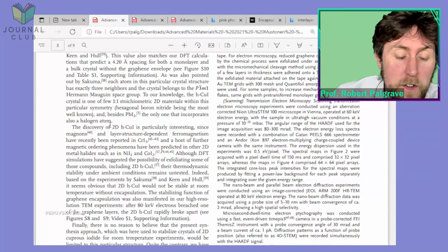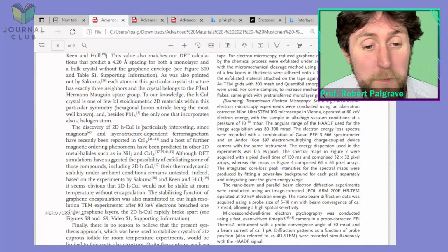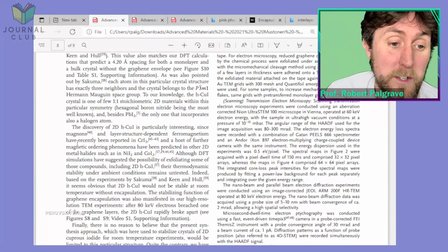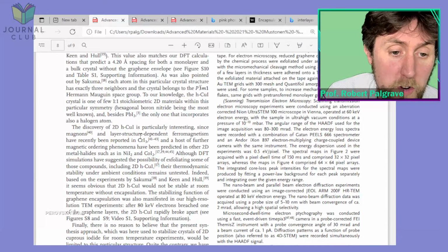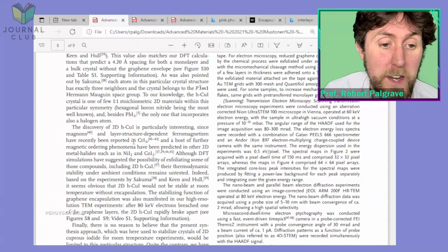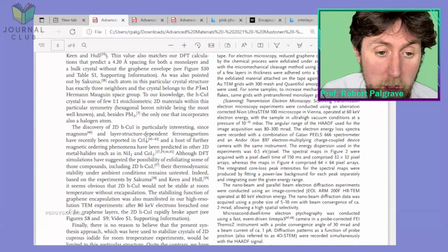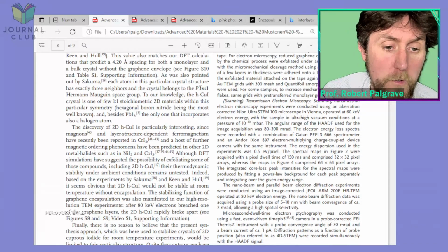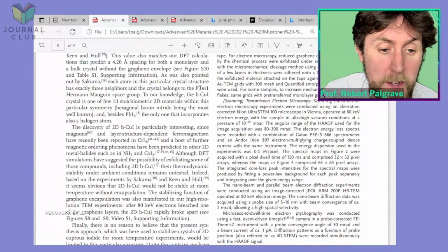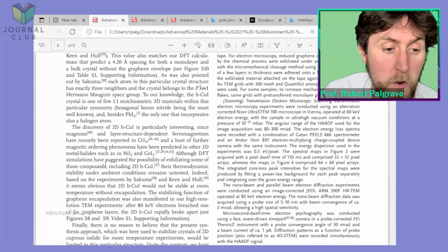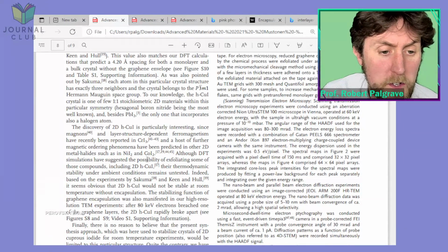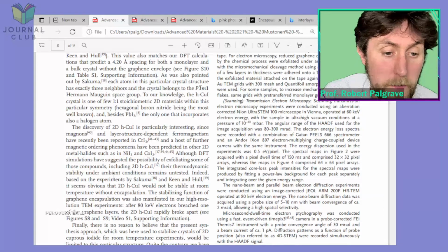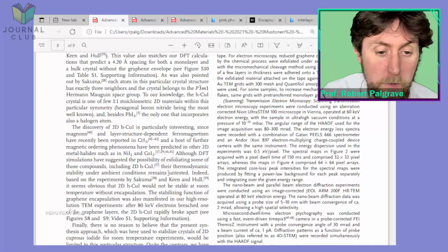The discovery of 2D hexagonal cuprous iodide is particularly interesting since magnons and layer-structure-dependent ferromagnetism have recently been reported in chromium triiodide, and a host of further magnetic ordering phenomena have been predicted in other 2D metal halides such as this and this. Although DFT simulations have suggested the possibility of exfoliating some of these compounds, the thermodynamic stability under ambient conditions remains untested.